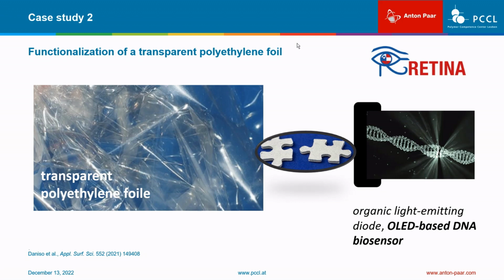However, the adhesion of short sequences of oligonucleotides used as bioprobes, which are needed to develop a genosensor on such polymer films, is rather poor. In order to overcome this challenge, we performed a physico-chemical surface modification of polyethylene films. Again, all the modification steps of the polyethylene surface were followed by Zeta potential measurements.